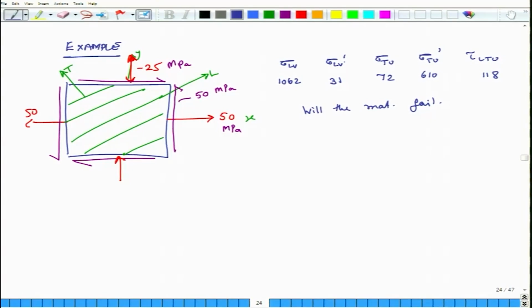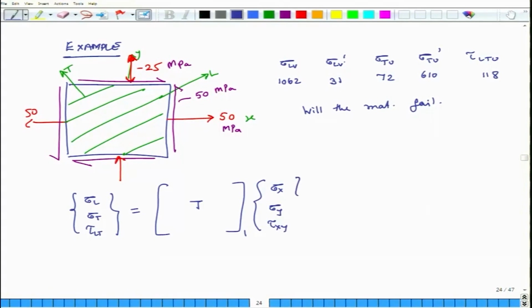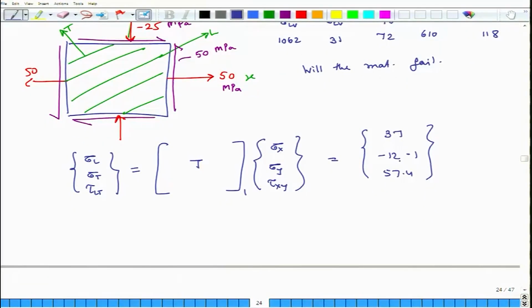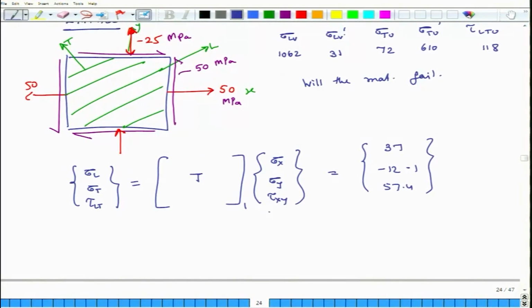So, what do we do? First, we compute sigma L, sigma T, and tau LT. This is nothing but the transformation matrix T1 times sigma x, sigma y, tau xy, and we know how to calculate this transformation matrix. We do all these calculations and we find that sigma L is equal to 37, sigma T is minus 12.1, and the shear stress tau LT is 57.4.